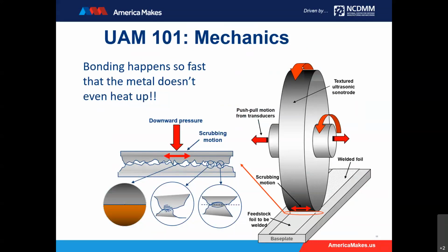The general idea is metals like to stick to other metals. But down here on Earth, all of our metals are coated with an oxide or a rust. What ultrasonic welding attempts to do is bring those two surfaces together and grind the nascent surfaces back and forth. That vibration is scrubbing away the oxide layer on the surface of the metals. We scrub that oxide away, we have virgin metal on virgin metal, a little bit of pressure, and we get a solid state bond. It's akin to an explosion bond or a friction weld in that it's a solid state process happening at very low temperature.